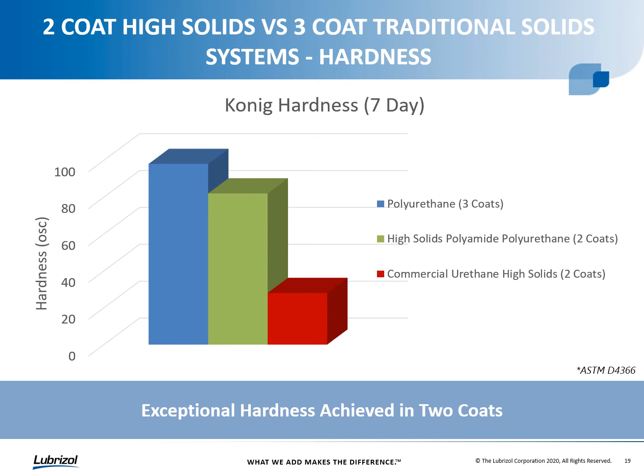And for having the good surface hardness, it has the very low Taber number. So you get that balance of good hardness, but very good abrasion resistance as well, similarly to the 3 coats of the traditionally lower solids PUD. And then comparing that against the commercial high solids benchmark product, we see it has much lower Konig hardness, so it's a much softer material, and it also doesn't have very good abrasion resistance, that it had the highest Taber numbers of the 3 samples tested. So again, we're able to achieve excellent hardness in just a 2-coat system.